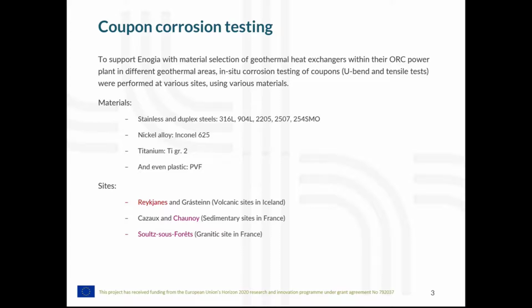And to start with, to support Enogia with the material selection within their ORC power plants, we performed in situ corrosion testing, and in situ means in a real environment. So we placed small material samples in different geothermal environments, kept them there for a certain amount of time, and then evaluated their performance. So we looked at the corrosion defects in the samples